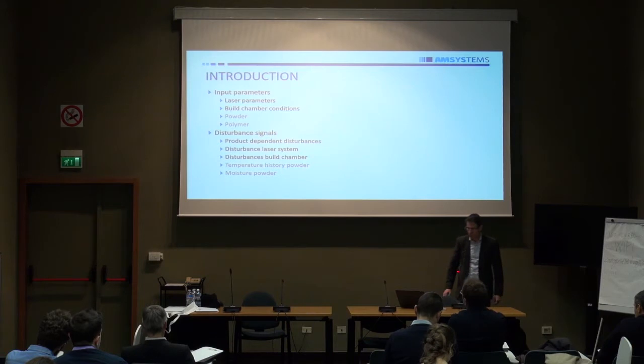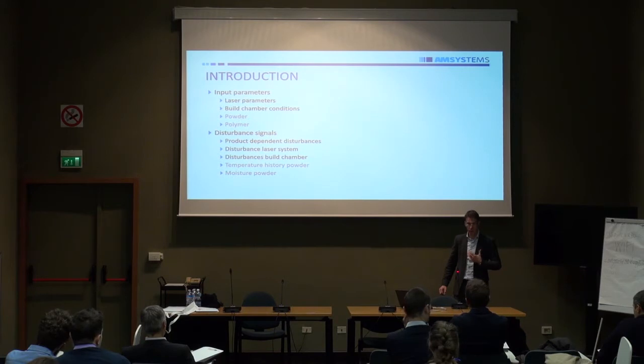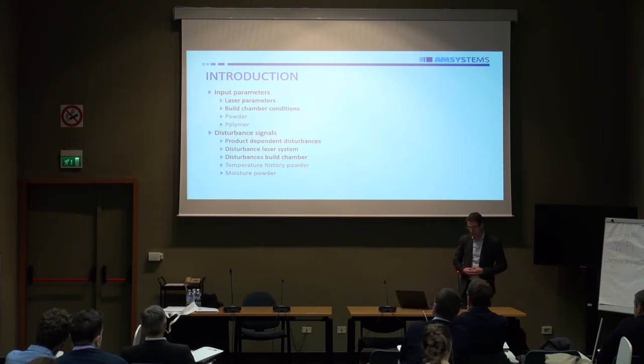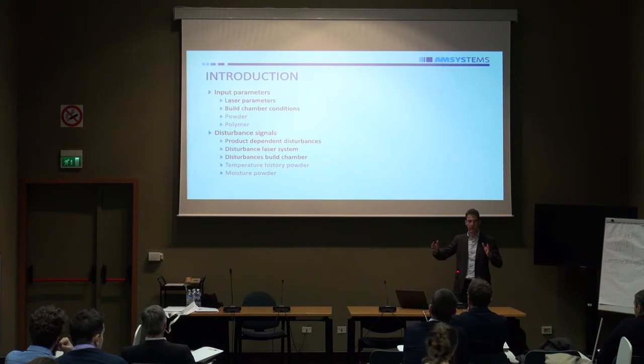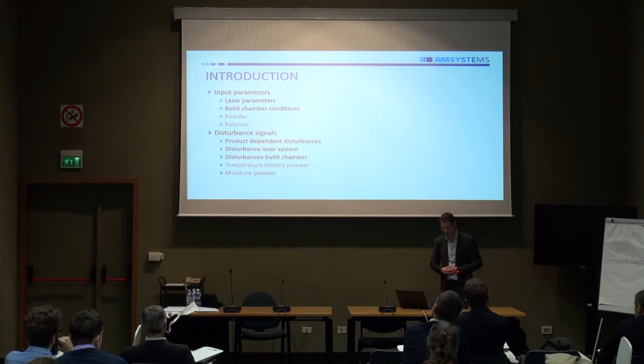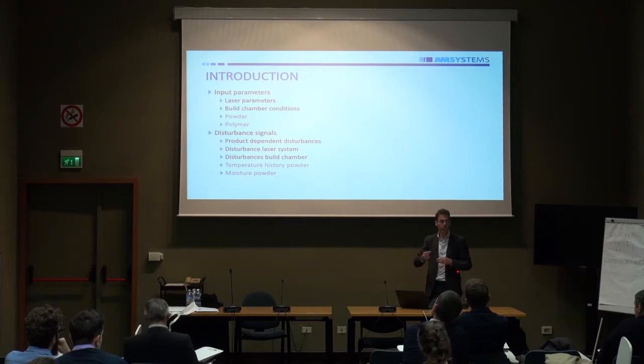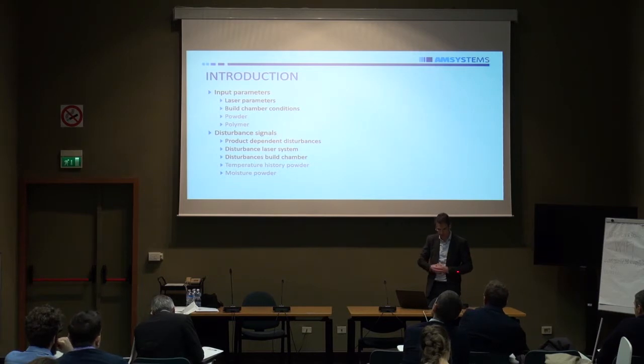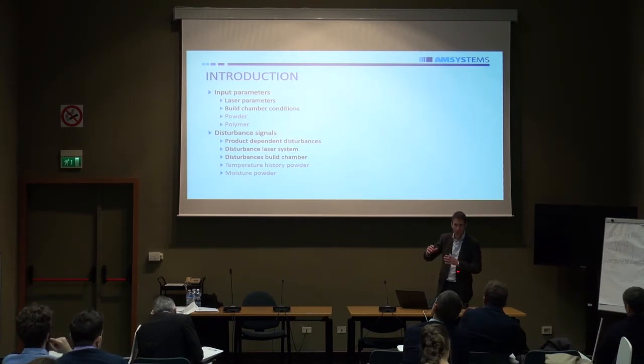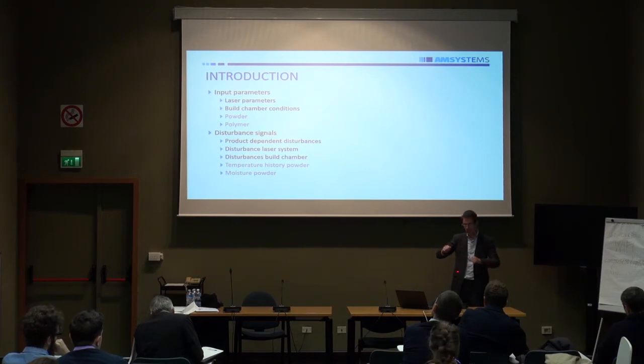And so what affects the quality of the part? If you look at this laser sintering process, of course, the laser power and speed have a big effect. Another aspect, as I said, is that this build box is at a certain temperature. So if you change it, it will have an effect on the quality. The powder you use, for example, the powder particle size distribution, has an effect. Which polymer you use. So these are all wanted inputs. You can design it, and this is the optimum.